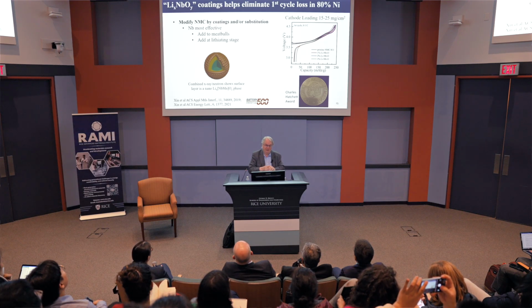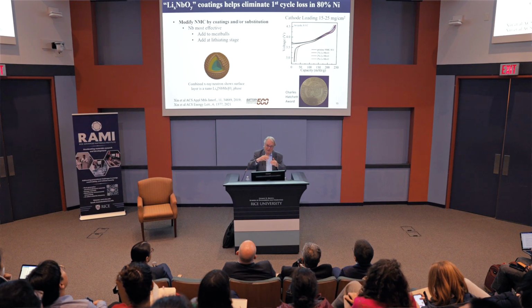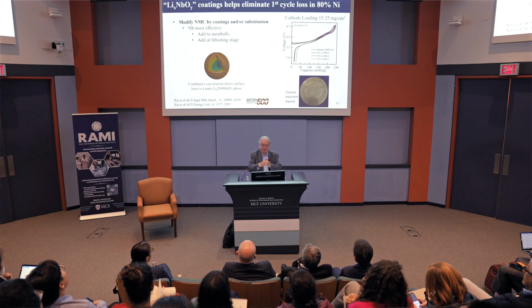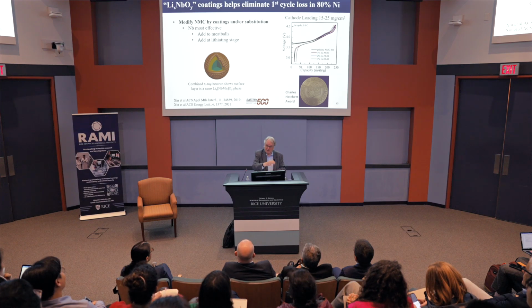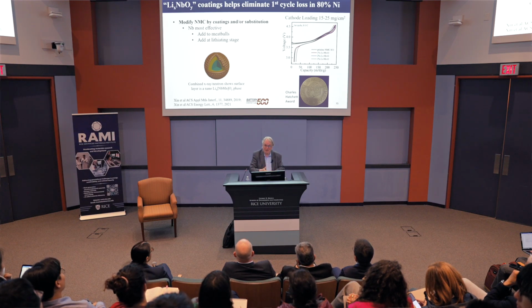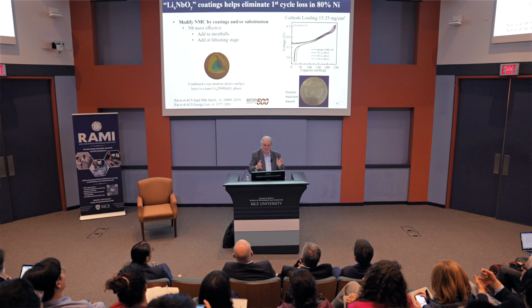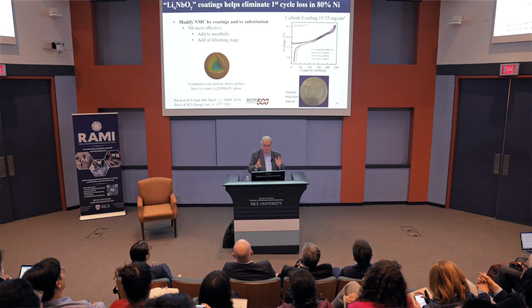And the other thing we found out when we put the niobium on the meatballs, either after the meatballs were formed or when we put lithium into them, a little bit of niobium went into the lattice, but some of the manganese came out. So the surface coating is a lithium niobium manganese oxide. It's not a simple thing. And we did this by a joint X-ray neutron diffraction study.